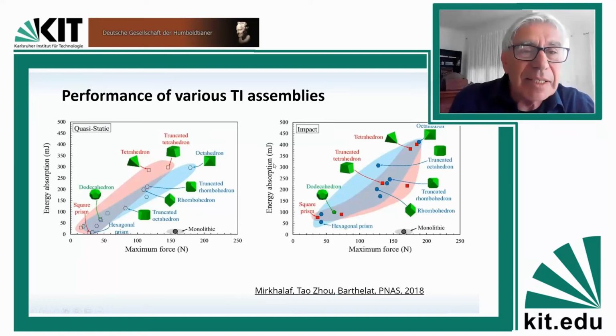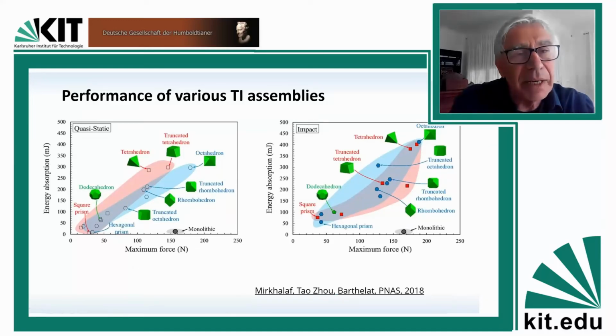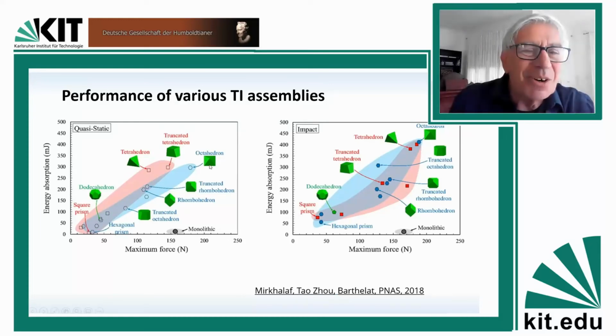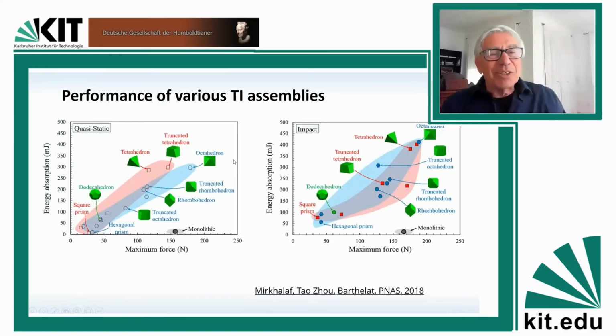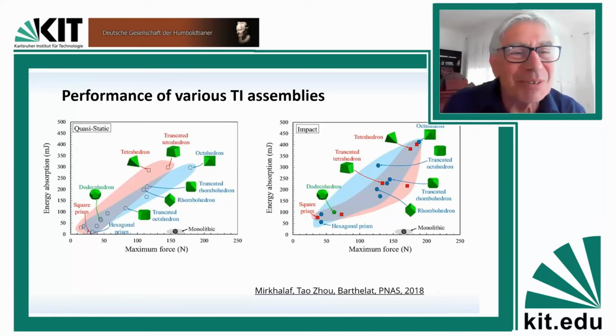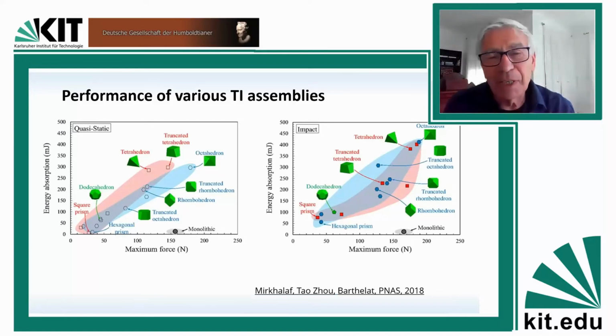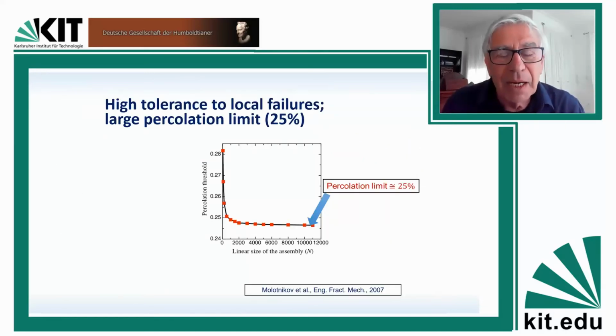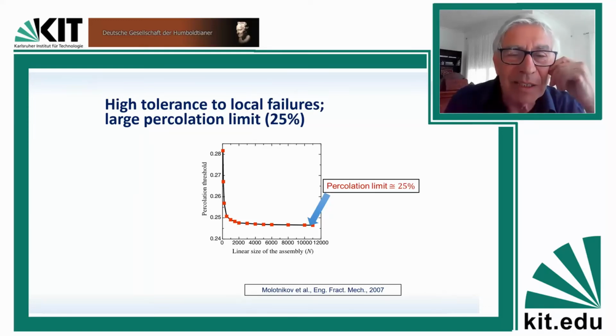Now, among the structures that have been tested so far, in terms of energy absorption and the maximum load that they can carry, the octahedra have shown the best combination of properties under both quasi-static and impact dynamic loading. But the space of such geometries is huge, so lots of things are unexplored, and there is a lot of room for the fantasy of the designer to further develop these structures. Oh, this is the picture that shows that you need nearly 25% of damaged blocks in the structure before you reach a percolation limit, when the fracture would propagate across the entire structure.